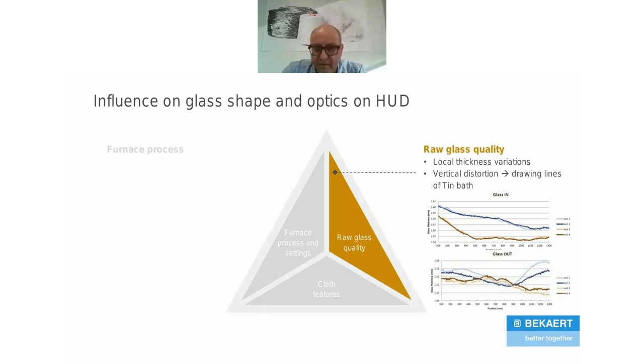And this is an example of four single plies where you can see a glass on the inner ply and then a glass on the outer ply. So four glasses on the inner ply, four glasses on the outer ply. You can see the different colors of lines. Here you can see there is a very big difference in thickness variation between the inner glass and the outer glass. If you look at the orange one, you can see that there are still two bumps. If you combine this with the inner glass, you will notice this in your reflective optics, and also in the transmission optics, you can already see a difference when you have something like this.